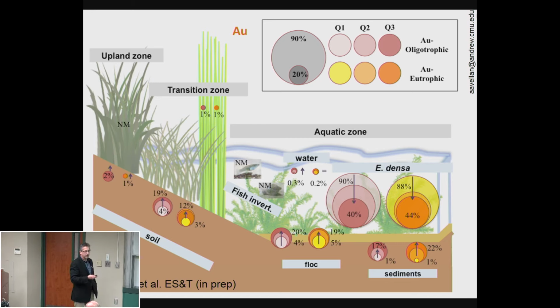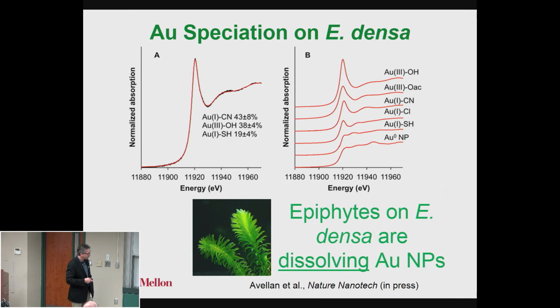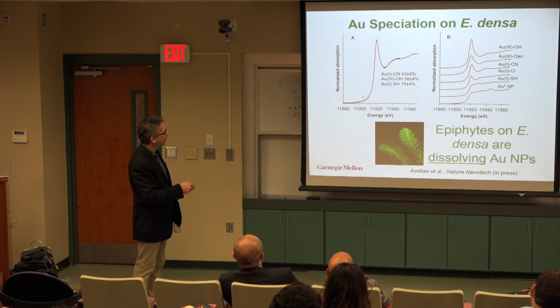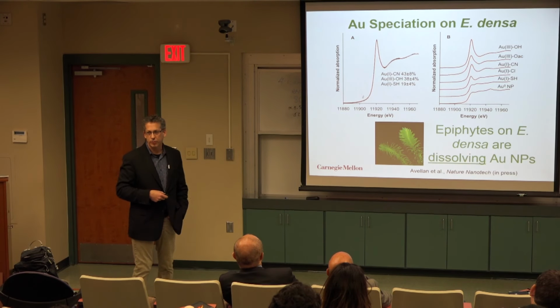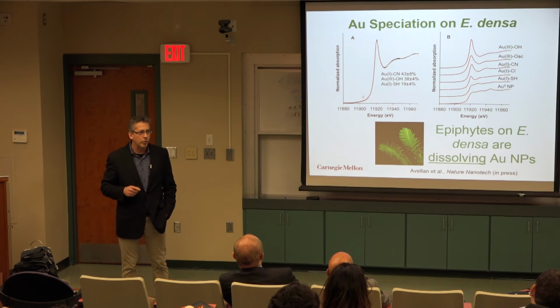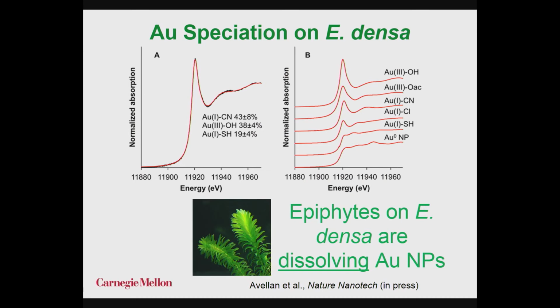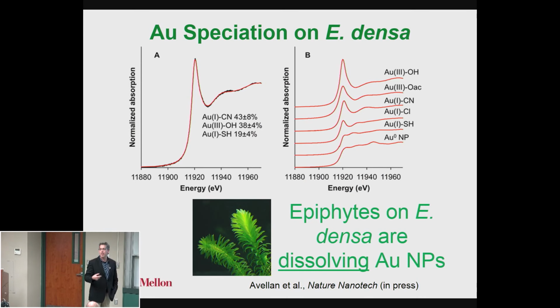So of course, we looked at it and we figured, okay, boring, we'll do X-ray, we'll find gold zero, and we'll move on. Well, it turned out when we did it, this was the spectra that we got of the gold inside these plants. It was gold 1 cyanide, gold 3 hydroxide, and gold 1 sulfhydryl. There were no gold nanoparticles. Those plants had taken my inert gold particle tracer and converted it, and changed it to these different species, which we never would have figured out if we hadn't done the X-ray absorption spectroscopy on it.